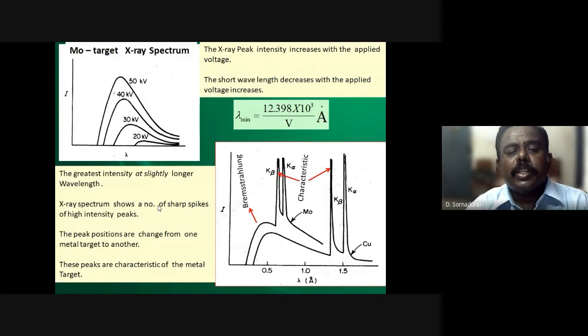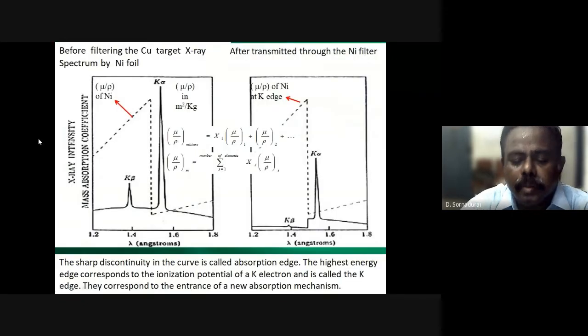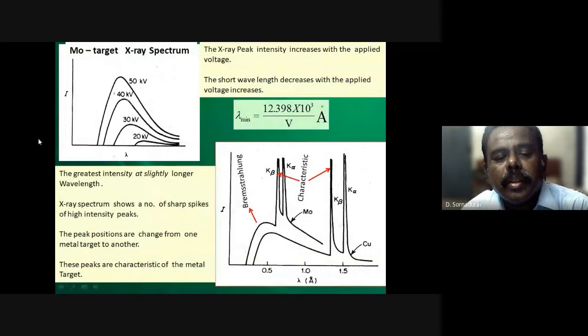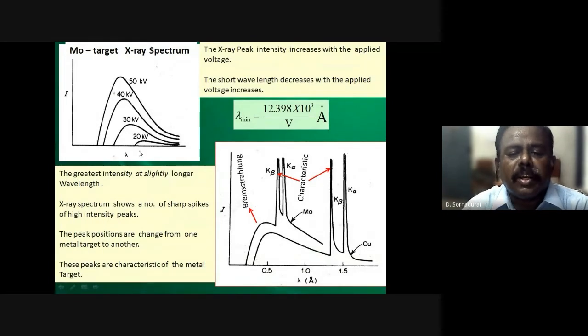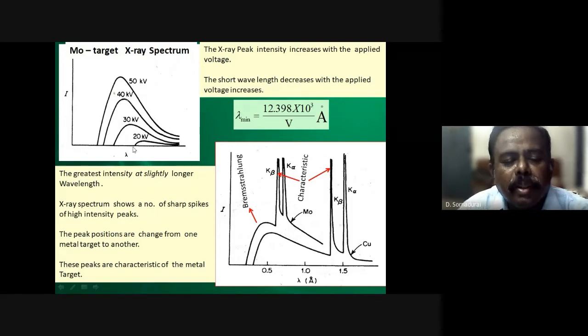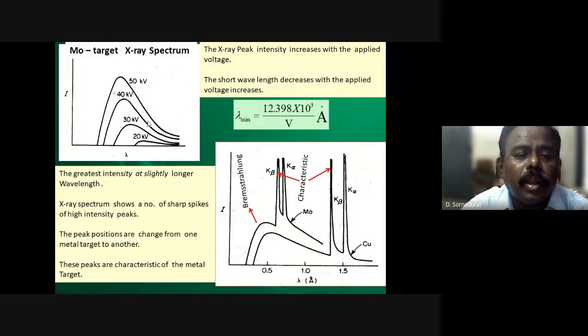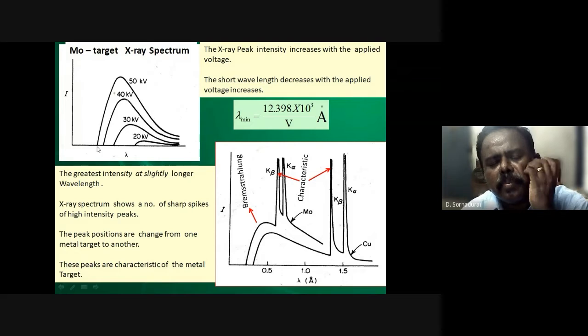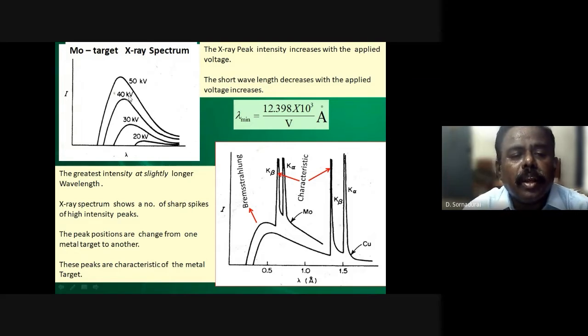So this is a typical molybdenum target continuous X-ray spectrum. You can watch here very clearly. At 20 kV, the intensity is very low, and the short wavelength limit is very high. When you increase the voltage of the tube, it shifts towards lower wavelength, and the intensity also increases. Similarly, going to 50 kV, you can see the short wavelength limit is very low, which means higher energy of the emitted X-ray, and the intensity also increases.